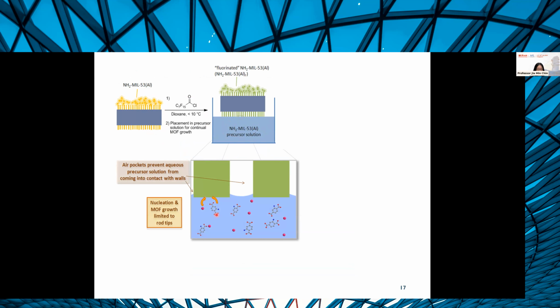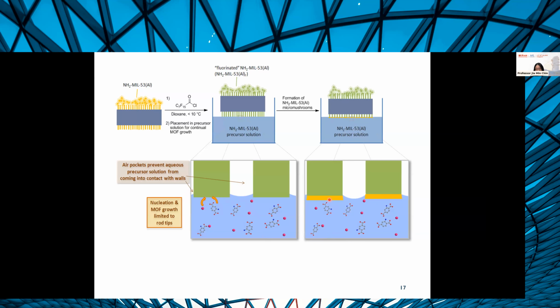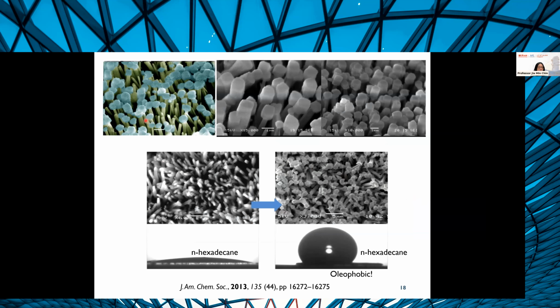And so what happens at this interface that's zoomed in here is that your air pockets really prevent this aqueous precursor from climbing up the walls. And so further nucleation and epitaxial growth is limited to the rod tips. The idea would be that we then grow these caps here. And indeed, we were able to do this with these little mushroom caps. And upon further fluorination of the caps, we end up being able to repel not just water, but also oil.